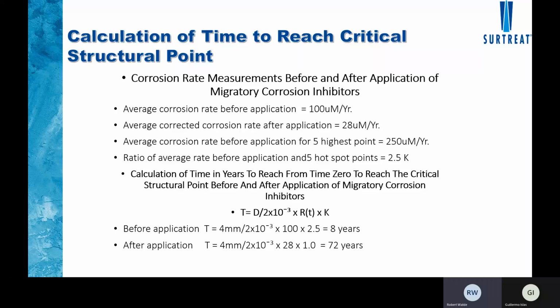So here we find that the original corrosion rate was 100 micrometers per year, and after treatment, the average rate dropped to 28, but the 5 highest corrosion rate points averaged at around 250 micrometers per year, such that the hot spots were corroding at 2.5 times the rate of the average. So that gives us a K factor of 2.5.